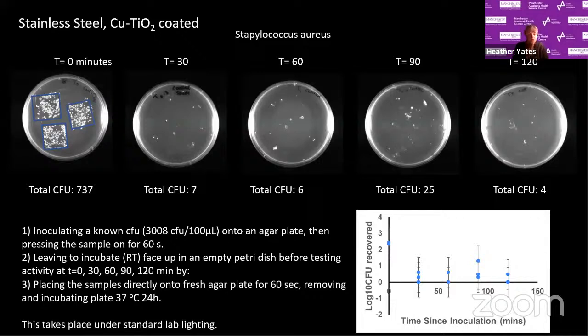Recently, we've taken on an MPhys student who's just started. And this is some work he did looking at my samples of copper titanium coated. And what we've done is to make this quite visual. We've taken agar plates, my samples, and what happened was a known amount of bacterial colonies were put on the surfaces. My samples were pressed into them, removed, and then put onto clean agar plates,